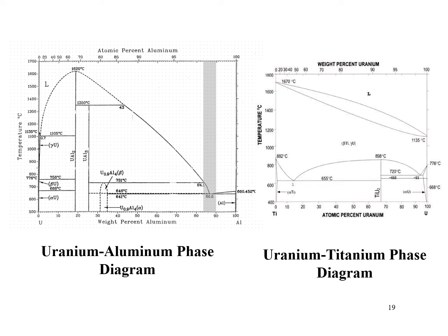Here is an example of two phase diagrams. We see the uranium and aluminum phase diagram. This is the liquidus phase. Here's uranium, here's aluminum, here's 100% uranium, and these are the different phases. If we start having mixtures, we'll form two phases here, one being the uranium metal and one being this intermetallic, uranium aluminum 2.